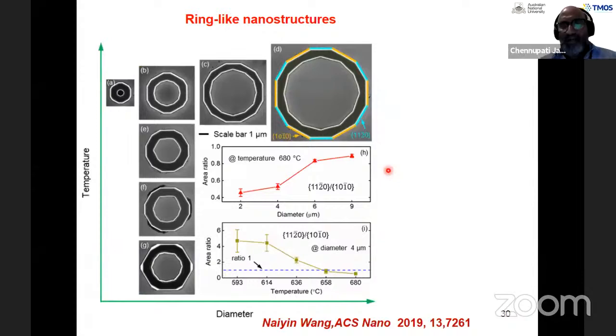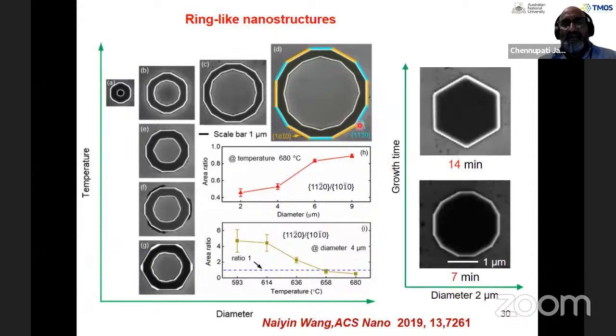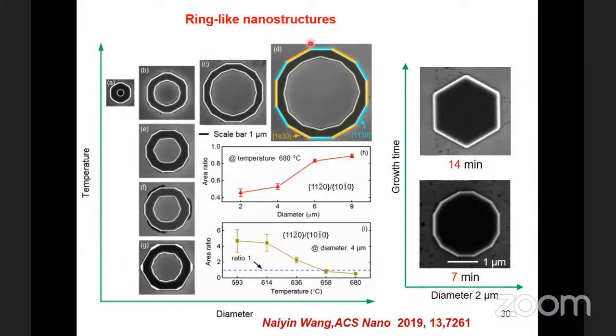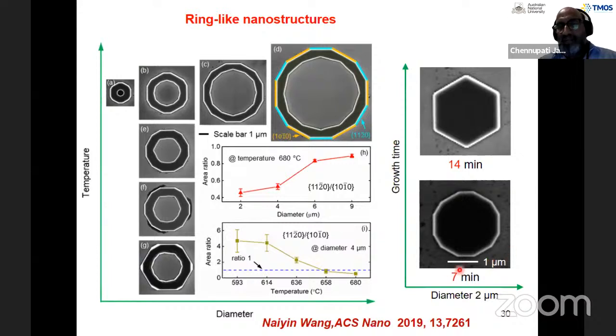What will happen if you open a ring? Again, Naiyin Wang has done that one, and you can see that you can get these beautiful alternating facets of these two facets which I talked about, and you can really start growing beautiful rings here. And in fact, we keep on growing. What happens is that you end up creating this membrane with these alternating facets again. If you keep on growing further, ultimately you finish off with these nice hexagonal facets.